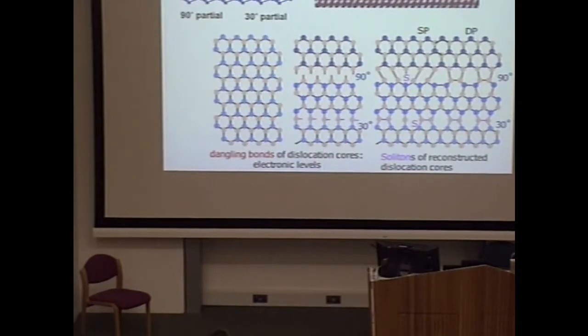This is the structure of dissociated dislocations in semiconductors: the 90 degree partial here and the 30 degree partial here. This is an HREM image of gallium arsenide. So there are two partial dislocations here, one and the second one here. And this is an image of dangling bonds. So this is the normal structure, with the 90 degree partial dislocation here and the 30 degree partial here.